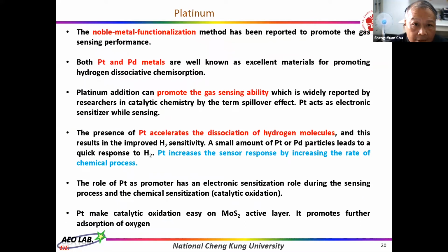Why did we choose platinum? Because the noble metal functionalization method has been reported to promote gas sensing performance, and both Pt and Pd metals are well known as excellent materials for promoting hydrogen dissociation and chemisorption. Platinum addition can promote the gas sensing ability, and the Pt can accelerate the dissociation of hydrogen molecules. Pt can increase the sensor response by increasing the rate of the chemical process.